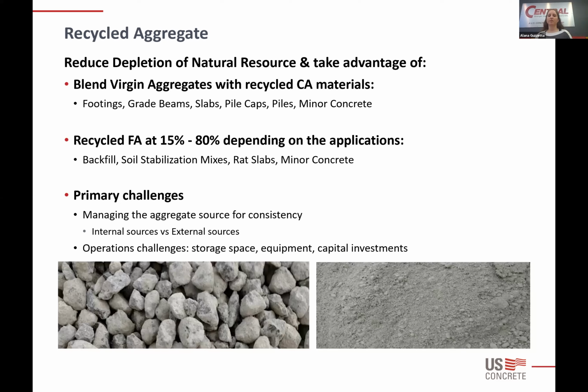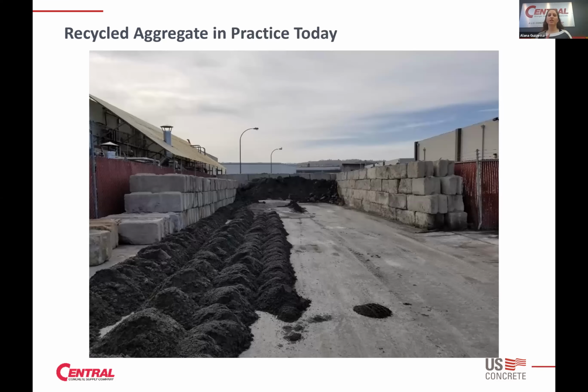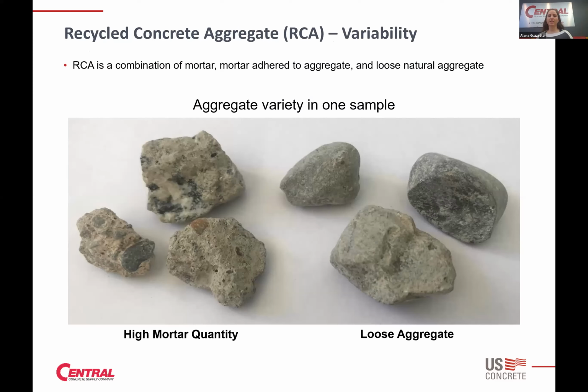But what this shows is concrete can be turned into recycled concrete aggregate, either as demolished concrete from a structure or as fresh concrete that gets returned, that's left over from a project, that can be laid out on the ground when it comes back to the yard, and then taken and crushed into an aggregate to be used in a new concrete mix later on. And this just shows the variability that you can get with recycled concrete aggregate. You can have some pieces that are going to have a high content. Some pieces are going to be loose aggregate that's loosened from the crushing process. Just making sure that you're managing the source, as long as you're doing that well, that's something that can definitely be used in new concrete and used with a lot of good quality.